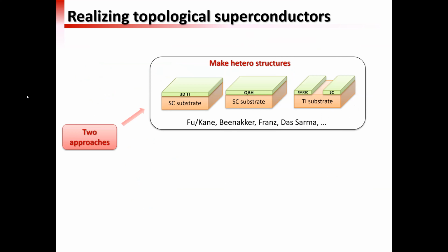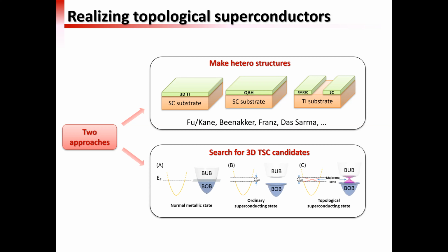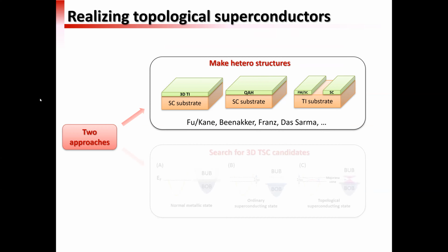Well, there are basically two broad routes to realize topological superconductors. One is to make heterostructures, man-made structures. For example, you have a superconductor substrate, and then you put the topological material on top of it, and then apply a magnetic layer or a gating layer to control all this and make a device out of it. That's pretty nice. There's also another route, the search for intrinsic three-dimensional topological superconductor candidates. I think people are exploring both routes. And in the past few years, the first route has been carried out very extensively. A lot of groups have been doing this.